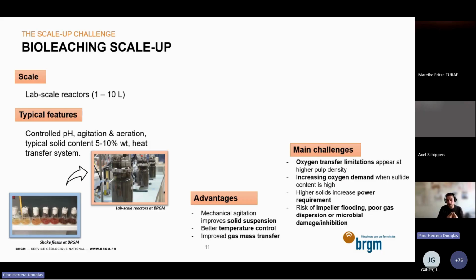And then we have a more controlled system. We have agitation and aeration that are more efficient, and we can increase the solid content to 5 to 10% in general. It can be a little bit more. And then we have a heat transfer system on the reactors, which will help us to understand the system better and to control these microbial reactions. So the advantages are improved mechanical agitation for solid suspension, and better temperature control and gas mass transfer.